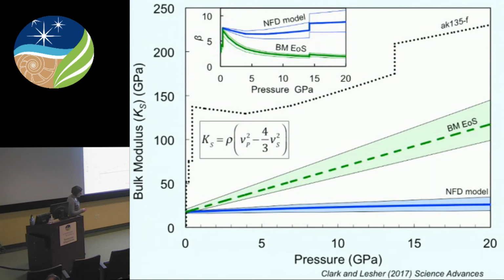So I've taken her model. Remember, it really only depends on these three parameters. I've calculated the bulk modulus of our silicate melt here with the network flexibility model. Here's our crystalline silicate mantle, the AK135F 1D global average model. And then here we have the Birch-Murnaghan equation of state, predicted bulk modulus as a function of pressure for silicate liquids. Not surprisingly, the Birch-Murnaghan equation of state sub-parallels the crystalline background mantle, because we're using the same equation of state for both the liquid and the crystalline phase.